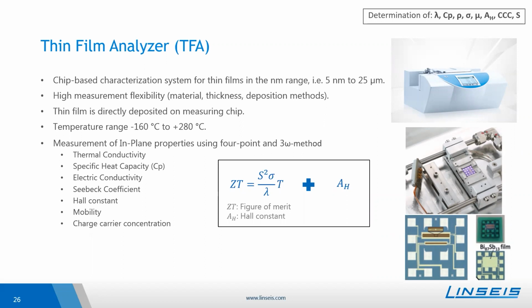And yes, so the properties are determined using a 4-point probe setup, and the thermal conductivity will be determined with the 3 omega method, and all the properties determined are in-plane properties. That's also an important point here, which needs to be mentioned. So the thin film analyzer is more or less an instrument for the complete analysis of a thin film regarding thermal conductivity and thermoelectrical properties.